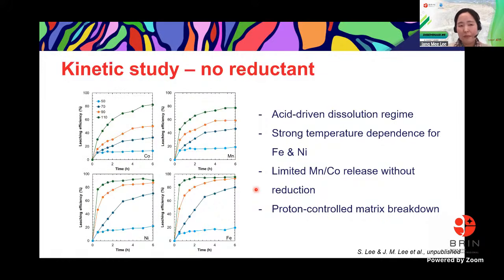So in previous leaching tests, we fixed the leaching temperature at 110, and then we just made a difference in terms of the addition temperature of the reductant and ore. But in order to conduct the kinetic study, we have to see the leaching behaviors at different temperatures, not fixing the leaching temperature at 110 Celsius. So this study is conducting the leaching test at different temperatures for the whole 6 hours between 50 to 110 Celsius. And this condition is without reductant, just nitric acid solution and adding the ore, and then to see how it goes.